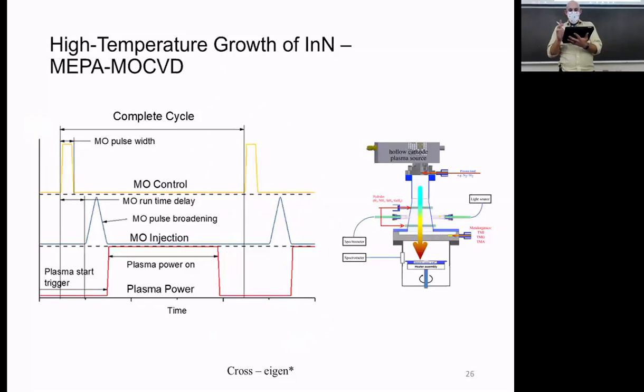And you can see now that what we did was we experimented with a lot of variables. We had the metal organic pulse width, which is the time that we allowed the indium, or the trimethyl indium, to come into the reactor. As it goes through the gas lines, it will dissipate a little bit and spread out. So you're not dealing with just a single on-off pulse, but it spreads out over time and then floods the reactor in that shape there. And then we would let it dissipate and get onto the surface. And then we would excite it with plasma and expose it to the nitrogen that came from the plasma.